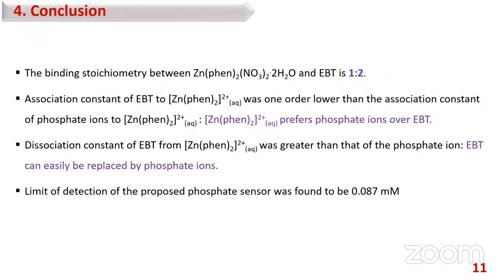Move on to the conclusion part. From my research work, I have concluded that the binding stoichiometry of the zinc phenanthroline EBT complex is 1:2. The association constant of EBT to zinc phenanthroline complex was 1 order lower than the association constant of phosphate ions to zinc phenanthroline complex. That means zinc phenanthroline complex prefers phosphate ions over EBT.